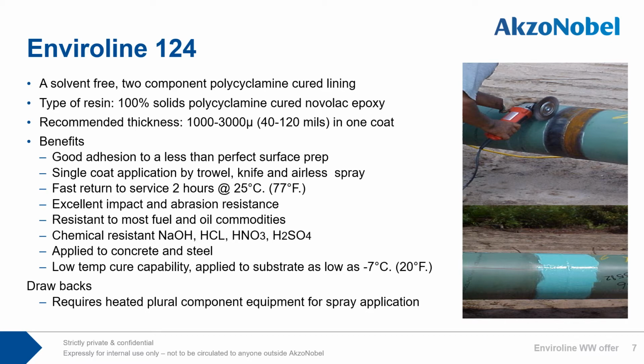Benefits are good adhesion to a less than perfect surface prep, meaning a high-tech product, low-tech application. Single coat application by trowel or knife, and for the most experienced, airless spray is available. Fast return to service in 2 hours at 25 C. Excellent impact and abrasion resistance. Resistant to most fuel and oil commodities such as gasoline blends, biodiesel, crude, and ethanol.